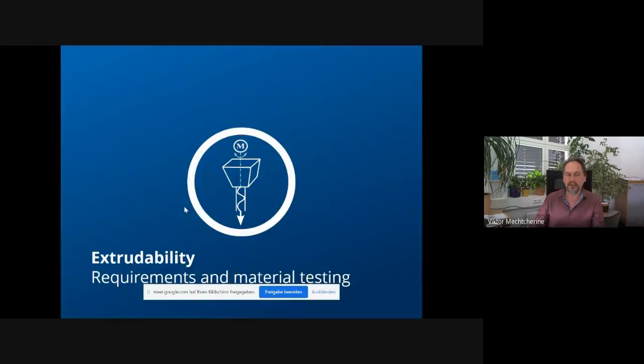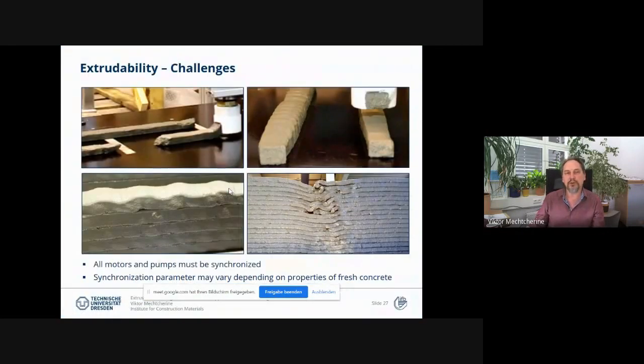Okay, it was pumping. And now let us proceed to the extrudability. And in this case, it's really about delivering exact amount of concrete per time interval or per time unit. So if you deliver too little material, you will have some interruptions in the filament. If you deliver too much material, you will have some kind of wave here. And of course, if it goes on from one layer to another, you will have accumulation of this imprecise material deposition and finally a severe damage of the structure.